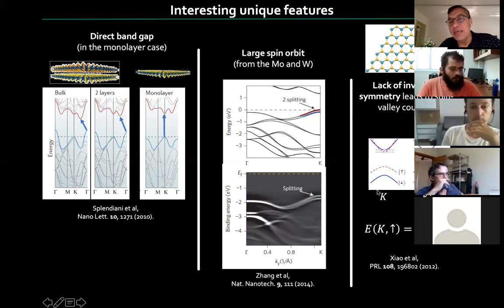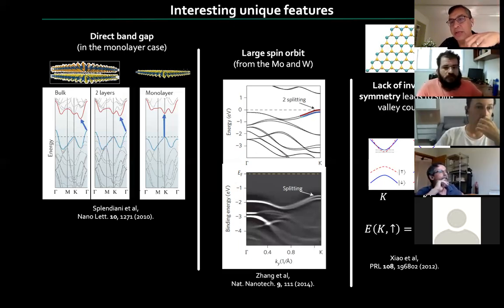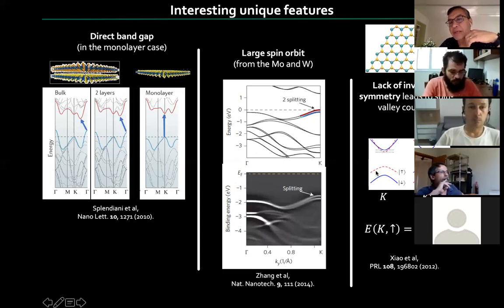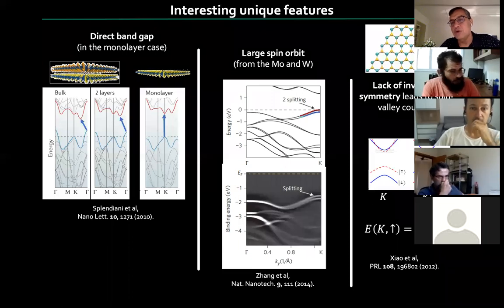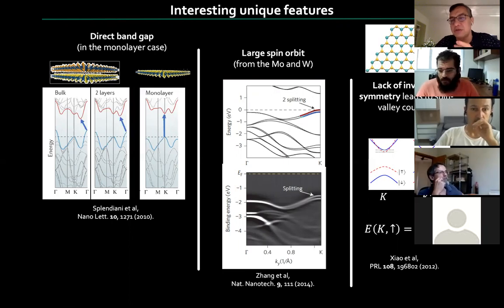So if you're in one K point, it's a triangular lattice. So the lattice is hexagonal, like that of graphene, kind of. So there are K points and gamma points and so on. But if you look at the K valleys, if you look at this K here, the dashed line involves spin up. And if you go to the time reversed momentum, which will be this K prime, there the spin has to reverse, right? To keep the spectrum time reversal symmetric. And so that means that the spin is kind of locked in the individual valleys, and it gives you polarization memories and a number of interesting features. So these are very interesting materials in that regard.